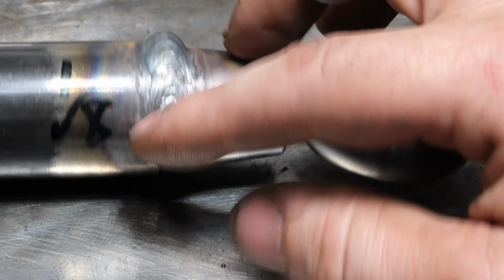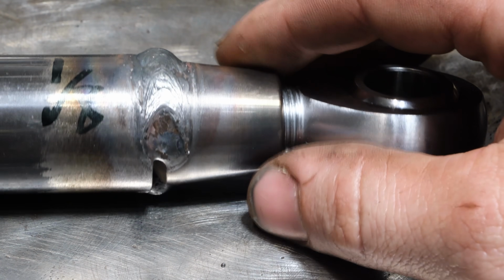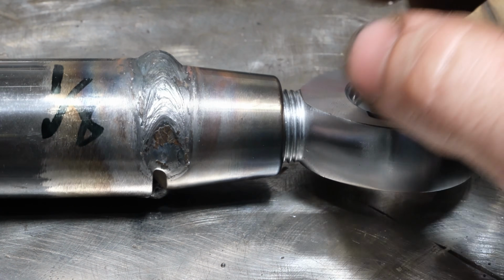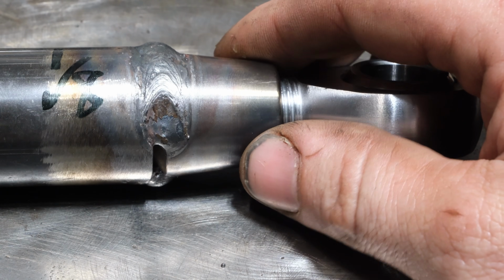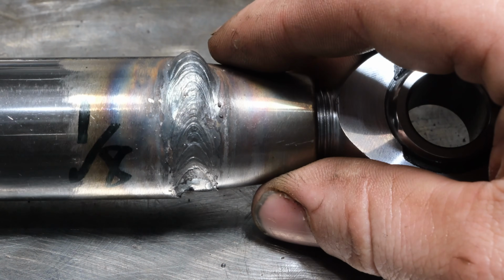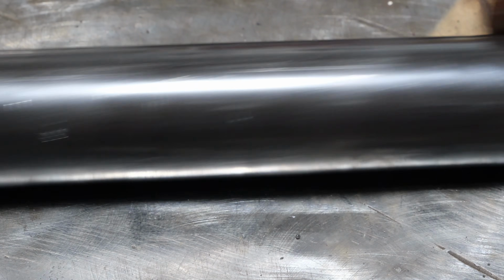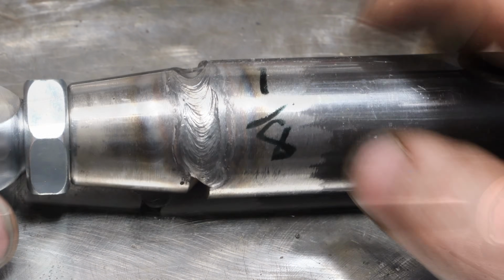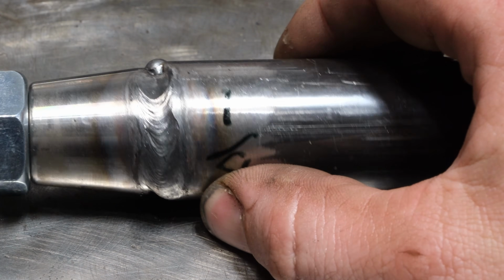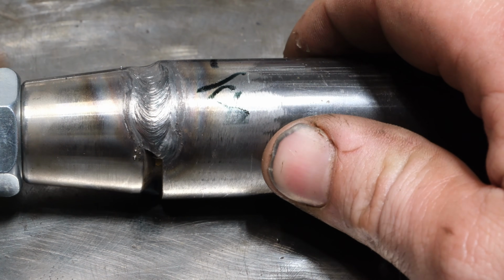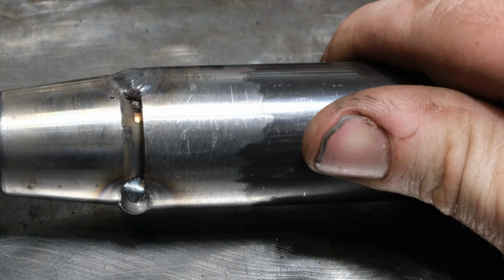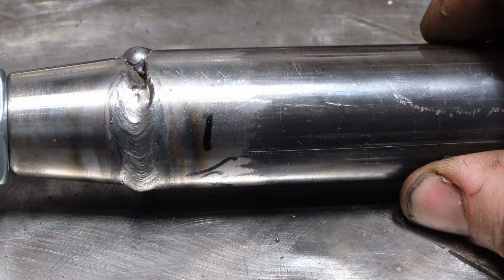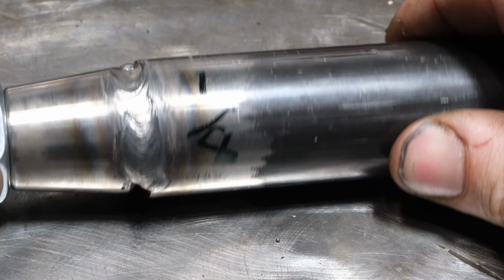So other than cold start, acceptable profile, we'll have to look at how the internals of it compares to the 3/32. That'll be interesting. Now over here, I have an 1/8 inch rod that I backed the amperage down on and enabled the hot start. You can see how much better the start is, and the overall profile looks pretty good.